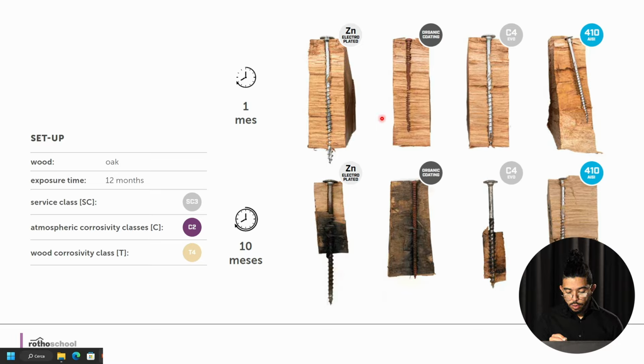You will see a little bit of tannins already attaching to the surface of the zinc electroplated, but as we saw before, that is not rust. So after 1 month, everything is okay with every coating and every material. After 10 months, the differences start to become a lot more present. The zinc electroplated has a strong presence of tannins, but you will see a lot of red rust.